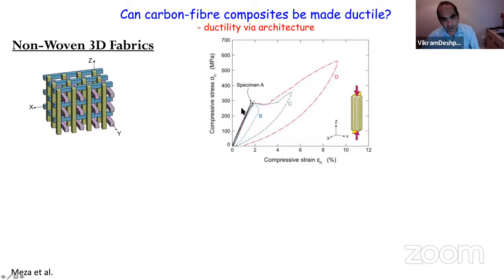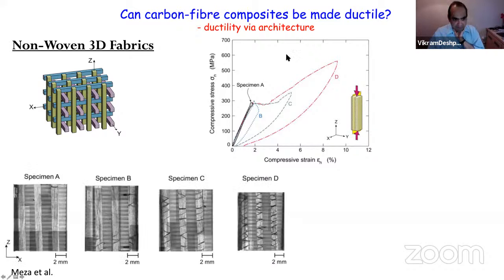There is, of course, nonlinearity. This was an elastic regime, and there's some nonlinear regime that's occurring here. And then when you unload, you are unloading to nearly where you started off. But there is no catastrophic failure that typically occurs in the compression of carbon fiber composites. And why is that the case? It's interesting because we're showing micrographs now of specimens A, B, C, and D after the unloading event.